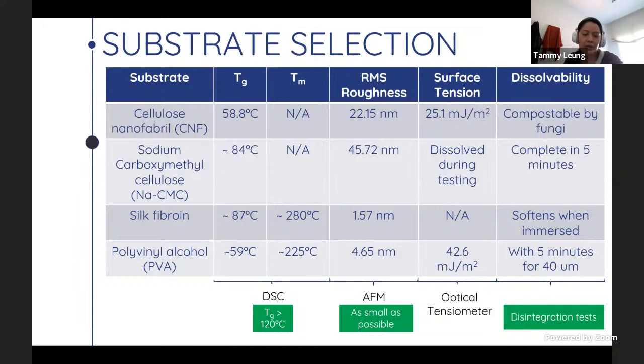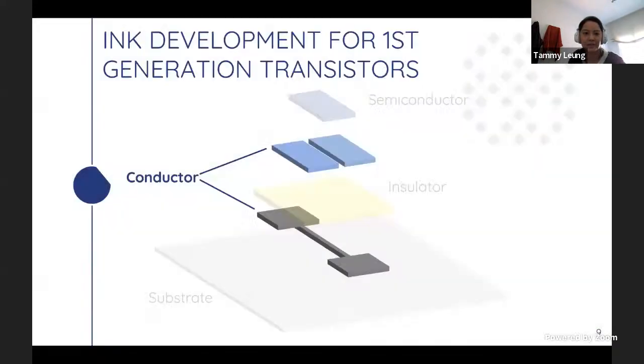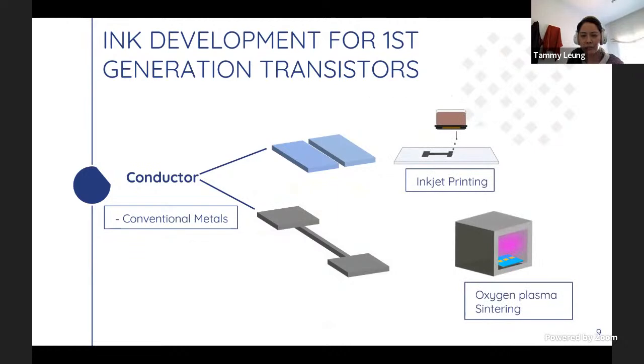Additionally, the sodium carboxymethyl cellulose was eventually eliminated as a material because of its extreme reactivity to water and its extremely high roughness. Therefore, all the rest of the remaining substrates were used for further testing. Again, because all of the chosen substrates had a glass transition temperature lower than 90 degrees C, we were then forced to adapt to be able to place a conductive layer on top that was within this temperature range. And this was done with conventional materials, as this is part of the first generation of transistors, and we accomplished this using inkjet printing and plasma sintering itself.